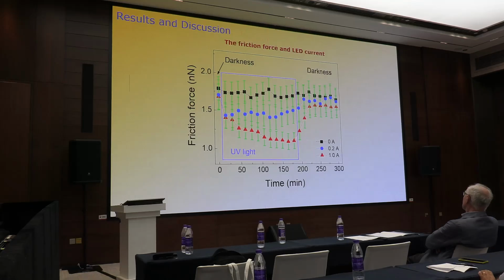Okay, it depends on the intensity because all the other experiments were done at a fixed LED current, fixed luminous flux. Here you can see that this is darkness. This is turning off the LED and then turning on at this current, and this is at this current. We have here a higher luminous flux compared to the blue one. You can see that when the LED current increases, the friction force is reduced. There is a dependence between the friction force and the luminous flux that the surface receives.